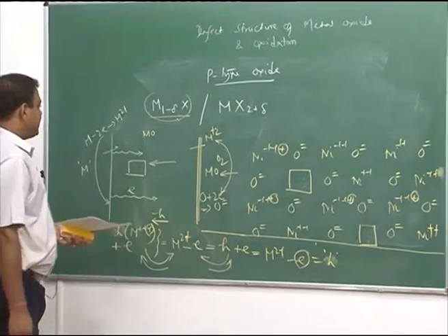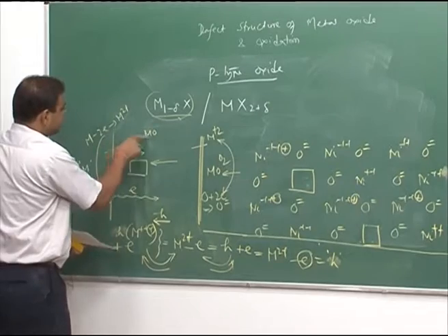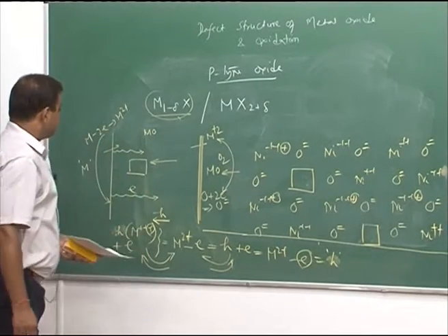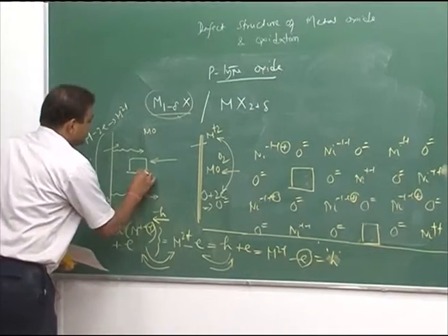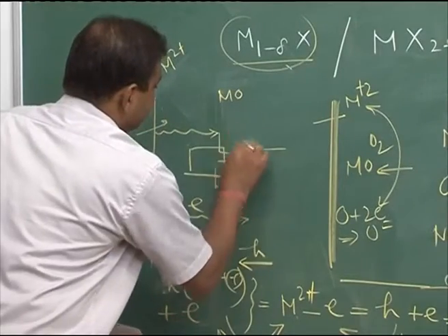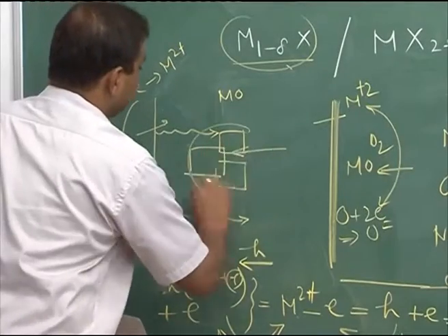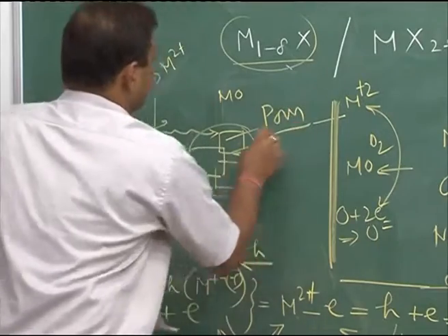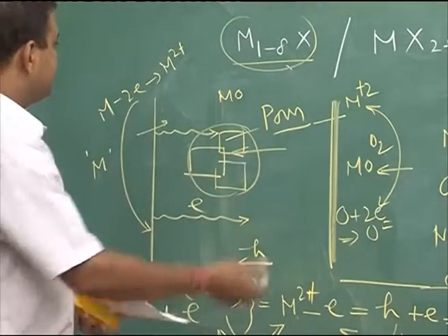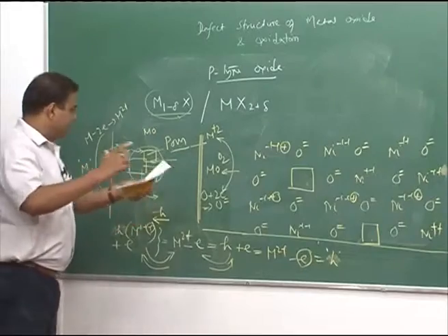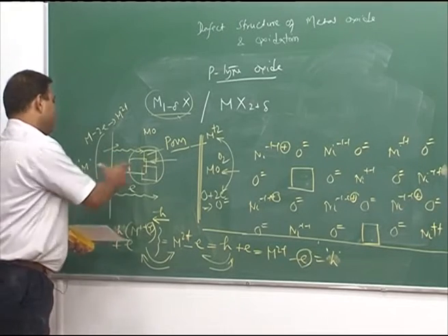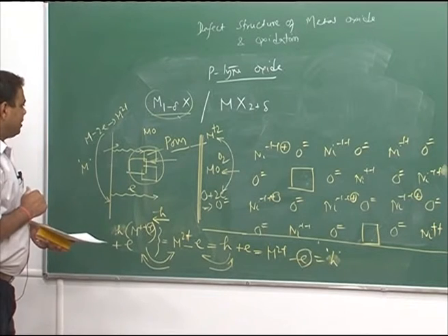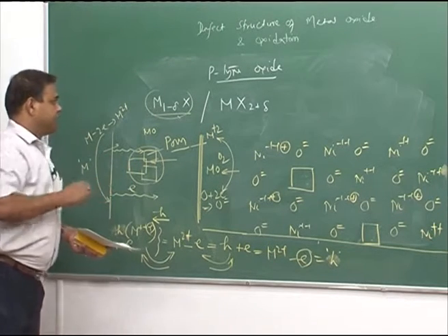The metal cation diffusion is taking place through the hole and metal cation interaction, and a couple of holes can combine and form a pore here. So, this is a pore. One pore can be created due to the combination of many holes, and this is the mechanism of how a pore forms in a p type oxide.